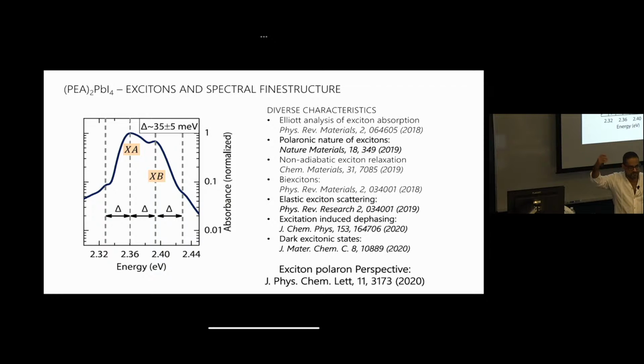The charge perceives the lattice through the motion of the phonon, through the lattice motion. In a small polaron limit, like in organics, you've got a very strong local coupling to a vibration that deforms the lattice around you. And so somewhere in between, that's what's happening here. But now we've got an electron and a hole that are interacting. That electron and hole individually may be dressed by the lattice, not necessarily in the same way.